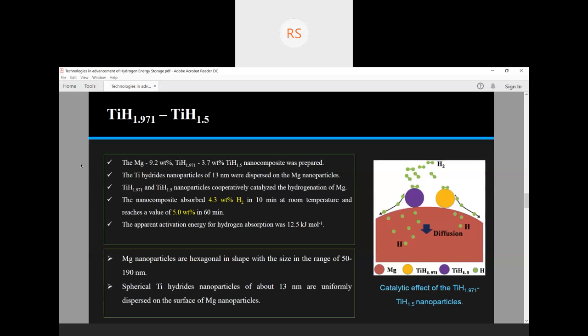The magnesium nanoparticles are hexagonal in shape with a size in the range of 50 to 190 nanometers. The spherical Ti hydride nanoparticles of about 13 nanometers were uniformly dispersed over the surface of the Mg nanoparticles. So the whole nanocomposite quickly absorbs about 4.3 weight% of hydrogen in 10 minutes at room temperature.